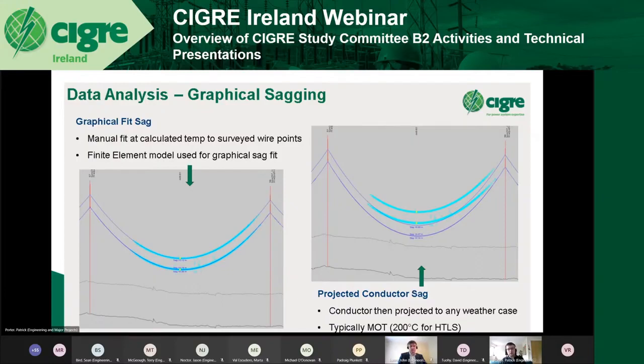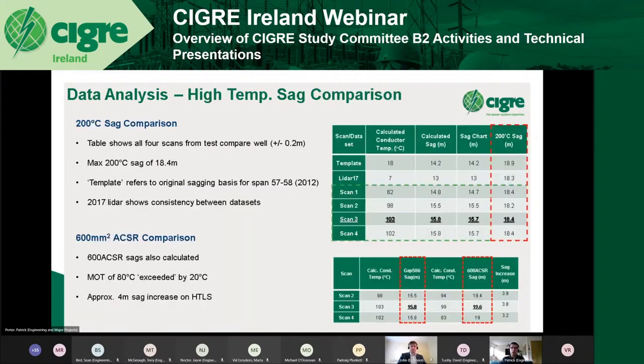Basically, what we would hope to find, and what should happen, is that regardless of what scan or what data set you're doing, after you do your graphical SAG and project to 200 degrees Celsius, you should get pretty similar results for each data set, and that essentially validates your approach and validates the behavior. And that's what we've done in this table.